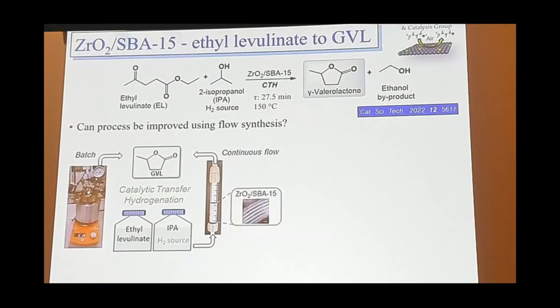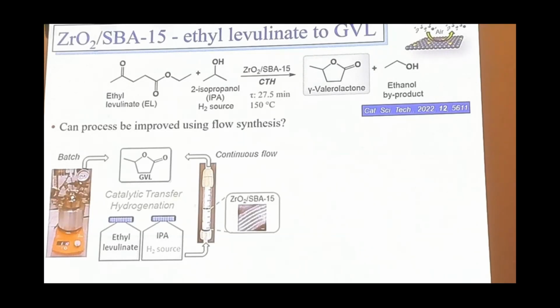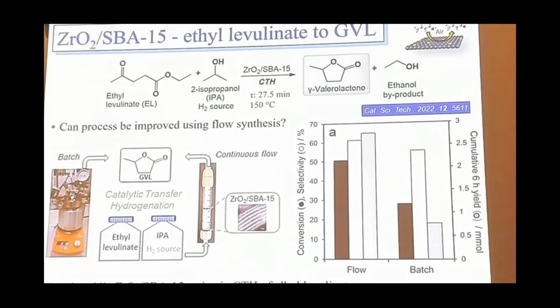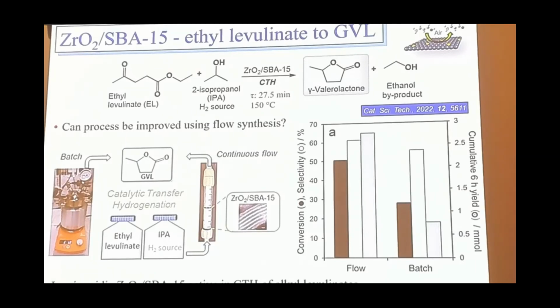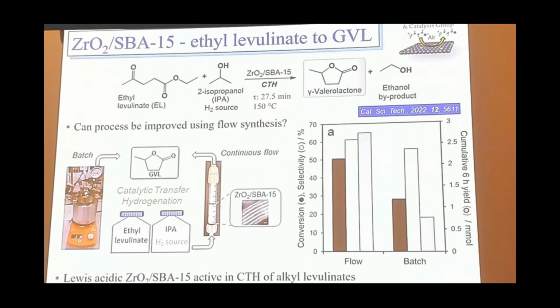We've compared 2 systems. So we have a batch reactor, and just a 1-pot batch reactor looking at about 150 degrees following this reaction. And then the other approach is we've got a continuous flow reactor with our packed bed of our zirconia SBA-15. We feed across this ethyl levulinate and IPA, and then monitor the formation of GVL. What we find essentially is that the Lewis acidity of our zirconia SBA-15 is very effective for the catalytic transfer hydrogenation. But what's most noticeable is when we work in flow, we get a significant enhancement in the cumulative yield of gamma-valerolactone than we do in batch.